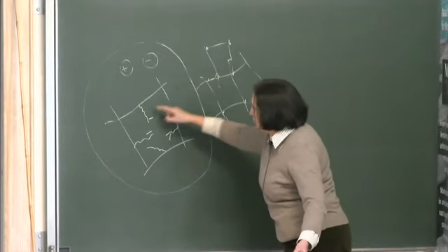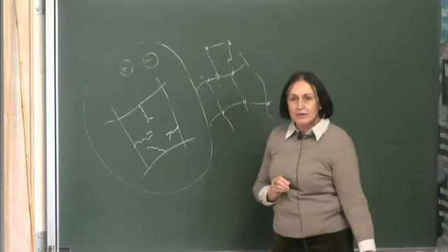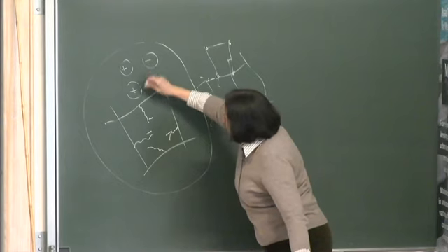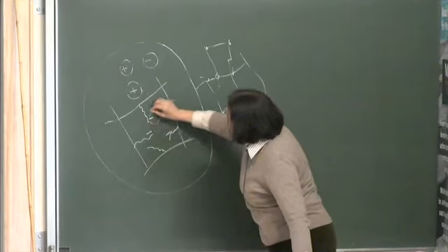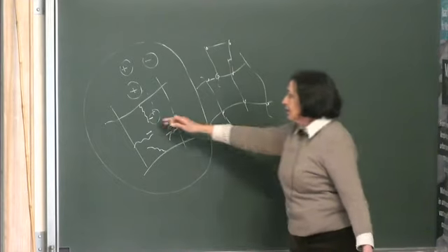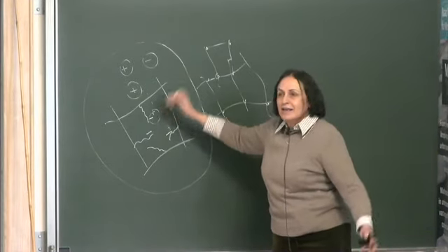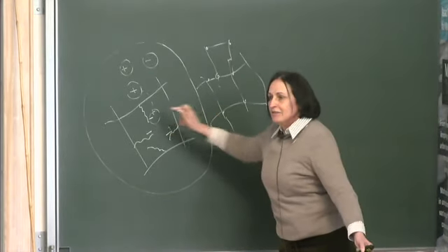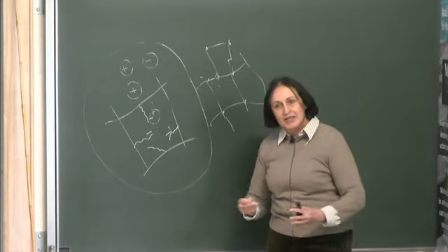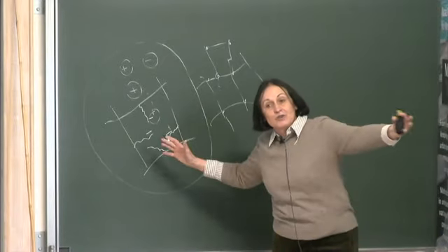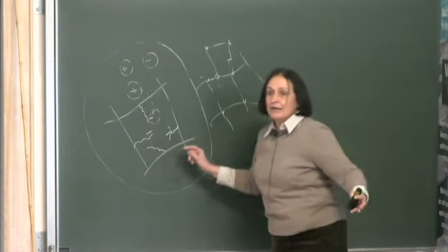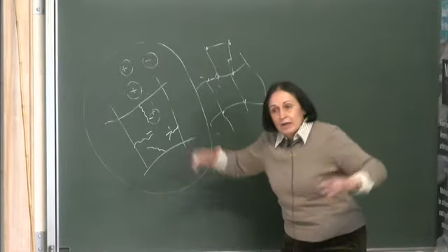So suppose that we have a situation where there's a lot of negative ions. These negative ions are going to call in the positive ions from outside, and they will keep neutralizing. So imagine the situation that we have to start with, very idealized, where everything was negative, that we just had the negative groups. In this case, these groups repel themselves so much that the polymer has to stretch. So then we pay a lot of elastic energy, because these negative groups have to be really very far from